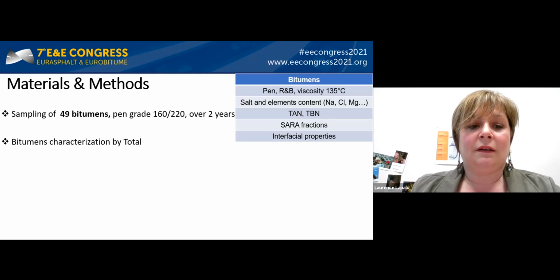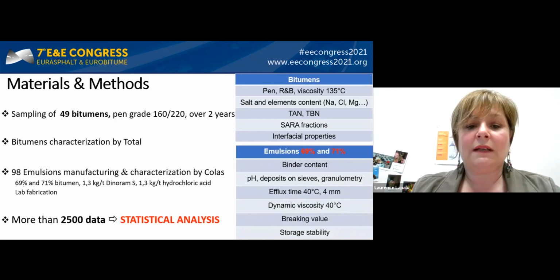We have collected 49 paving grade 160-220 bitumens over 2 years in different refineries. The bitumen characterization has been made by Total, and for its part, Colas was in charge of the emulsion manufacturing and characterization. In order to maximize the viscosity variations, we have decided to manufacture bituminous emulsions containing 69% of bitumen and 71% of bitumen. The emulsions were manufactured at lab, and we have manufactured 98 emulsions.